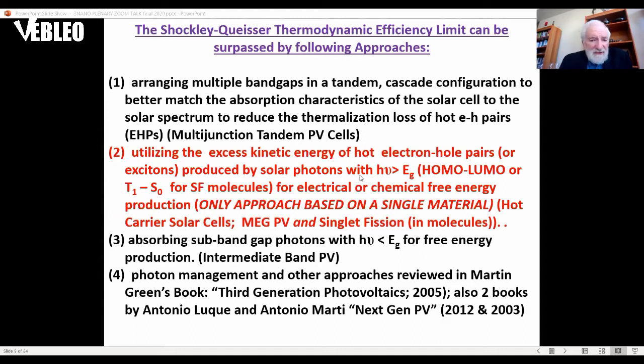Or also, I might mention briefly that this can be achieved in molecules, and this is called singlet fission, when you can convert a single photon into two or more, generally two, triplets, when the triplet state is halfway between the ground state of the molecule S0 and its first excited state S1. The triplet energy, if it's halfway between that excitation from S0 to S1, can produce two triplets from a single photon, and those triplets can be split to produce electrons at that energy, half of the singlet